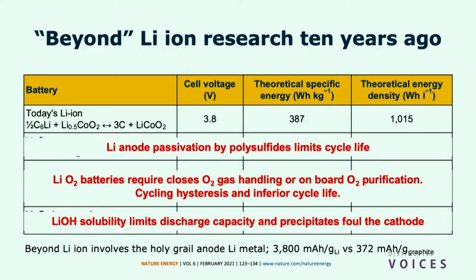And then for lithium oxygen aqueous, this has a liquid electrolyte. The solubility of lithium hydroxide in the liquid electrolyte is rather limited, and that limits the capacity. And also those precipitates of solid lithium hydroxide would foul the cathode. So those are the practical limitations to those beyond lithium ion technologies.